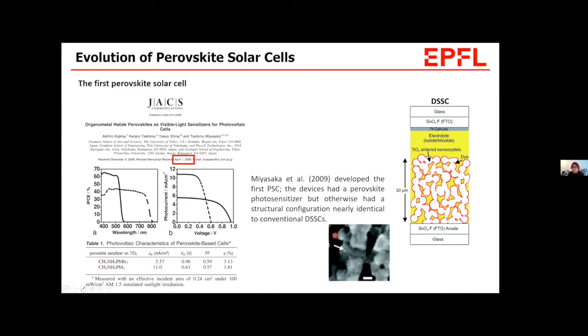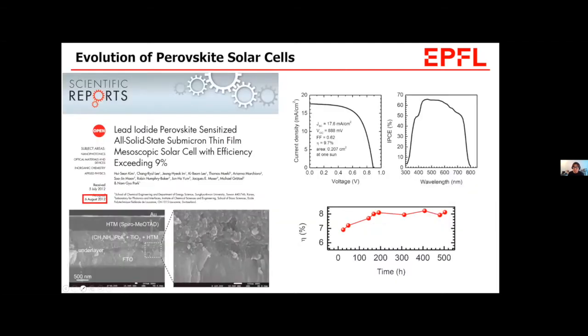The problem here was the dissolution of the perovskite, of course, because they still used a liquid electrolyte in this DSSC structure. And this problem was solved by replacing the liquid electrolyte with a solid-state hole conductor. It was spiro-OMeTAD on top of the perovskite layer.